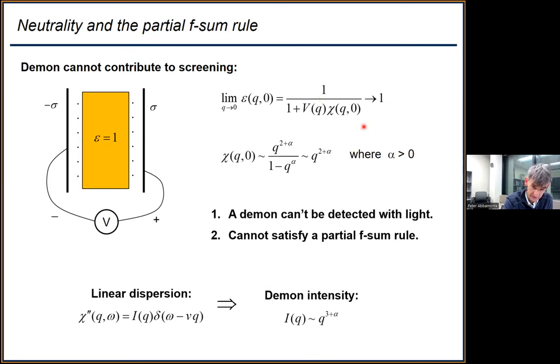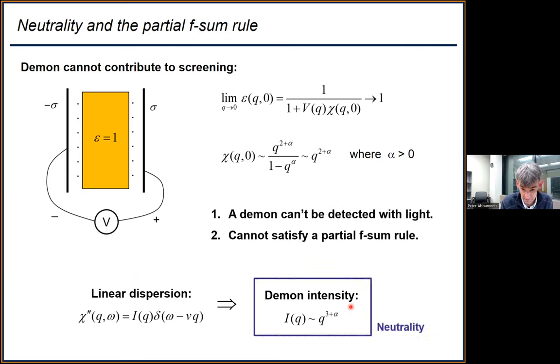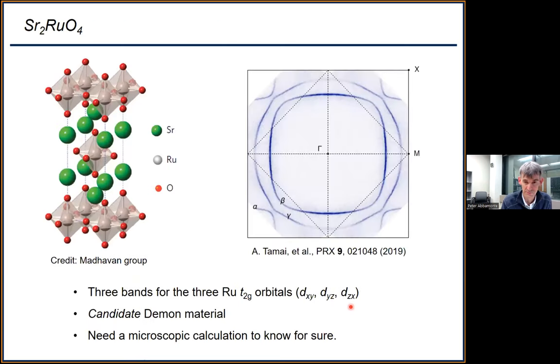And then I insisted that it follow this kind of functional form, with the real part and the imaginary part being related by Kramers-Kronig. It implies that the intensity of the demon would have to go like Q to the 3 plus alpha, where alpha is some number greater than zero. So it's just a secondary check. Okay, so that's the technical part, but that's the signature of neutrality. Also, it would have to be neutral to be gapless. So if you see something gapless and it's electronic, it's got to be neutral. Anyway, all this stuff needs to work for it to really be believable, in my opinion.